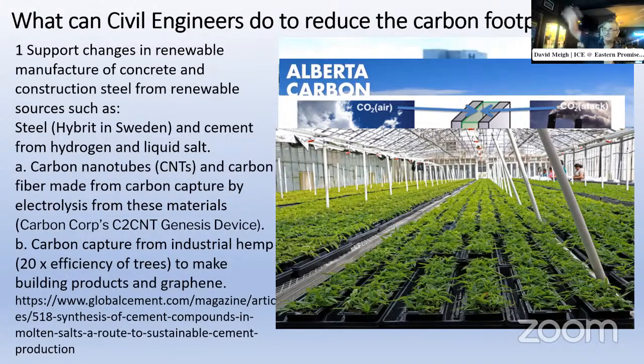So grown in a very long greenhouse where you feed in the carbon dioxide, say from a coal-fired plant or a steel plant, it can, not so much when it's young, but once it starts to grow, capture carbon very quickly. And then we can use the fiber from this material for all sorts of construction projects, which I'll show in a second. This material can also be used to make graphene. There's a company in Canada also making graphene from this material. I'm not quite sure what the process is. I put the internet link down at the bottom.